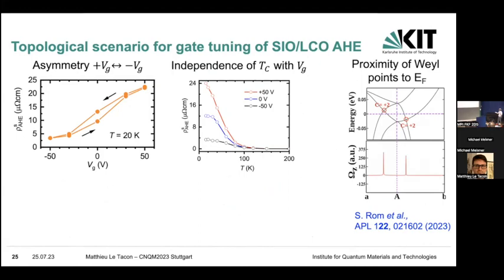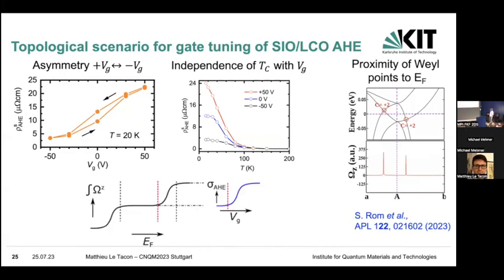And so if you put this together with the calculation that tells you that the Weyl points in the tetragonally distorted strontium iridate are quite close to the Fermi level, only 10 milli-electron volts away or something like that, you can see why, when you increase the charge carrier density and move your Fermi level away, you can go across some of those peaks in the Berry curvature. Because the anomalous Hall effect depends on the integral of the Berry curvature, you will have a certain increase of the anomalous Hall effect.